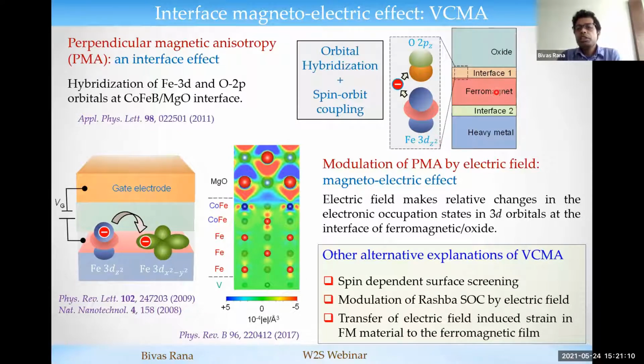Because this is an interfacial effect, if the thickness of the ferromagnet is limited to 1 nanometer or so, then the spins prefer to align in the out-of-plane direction. Okay, and this is the origin of the perpendicular anisotropy in this heterostructure.